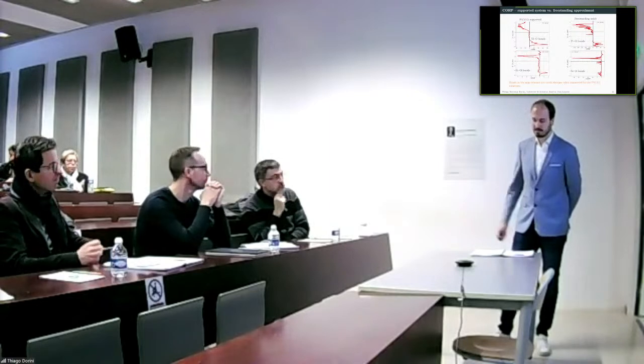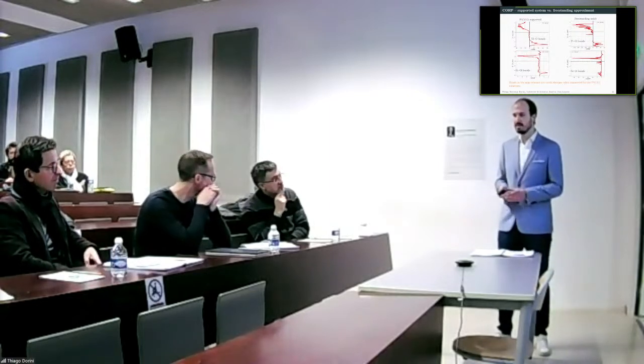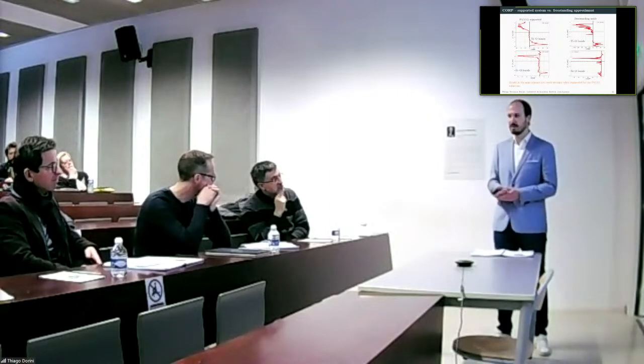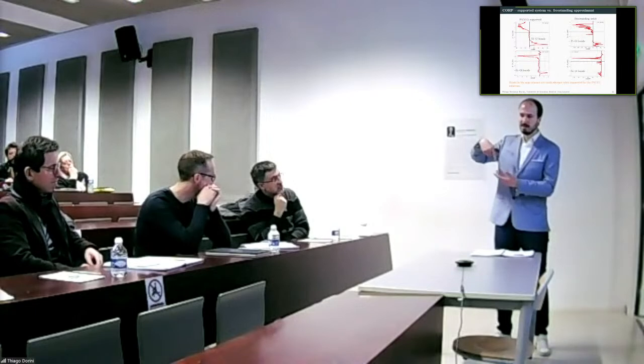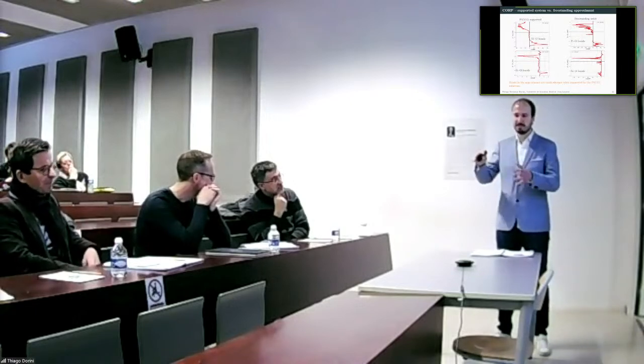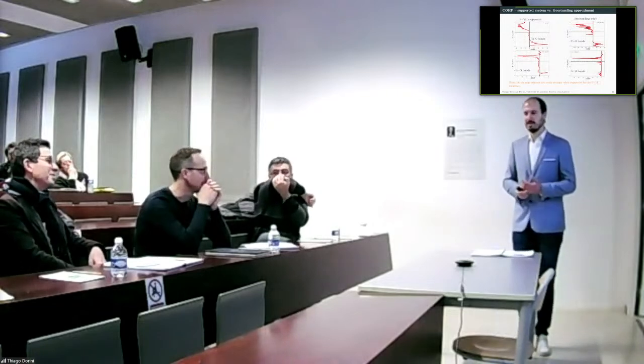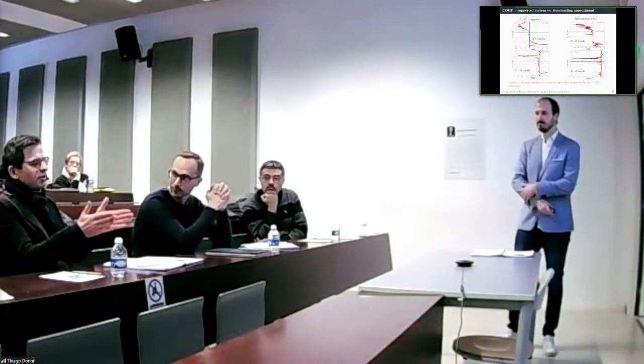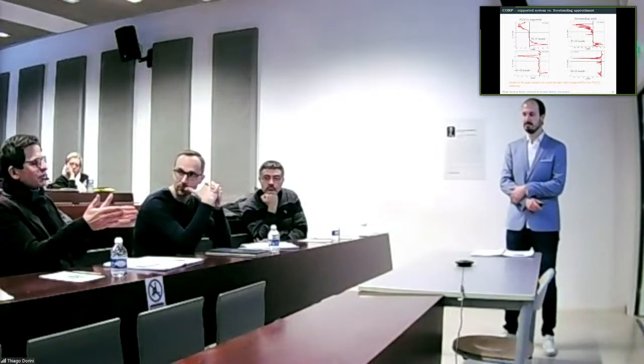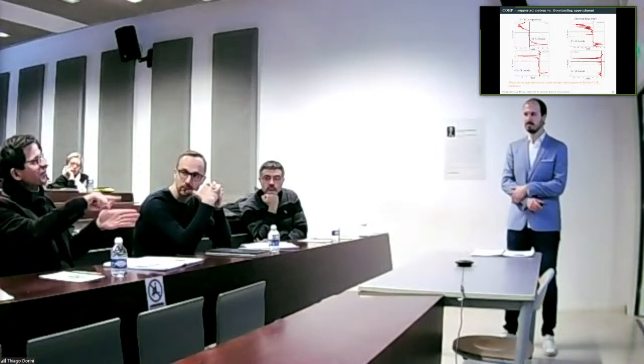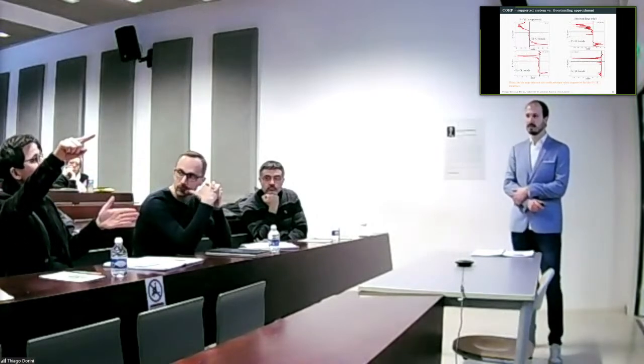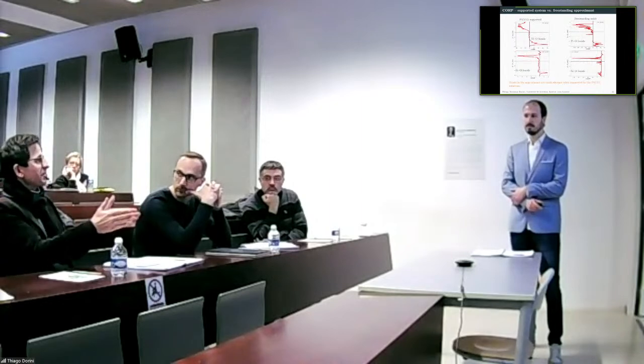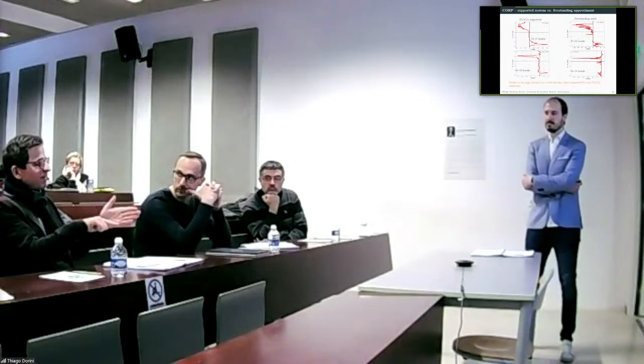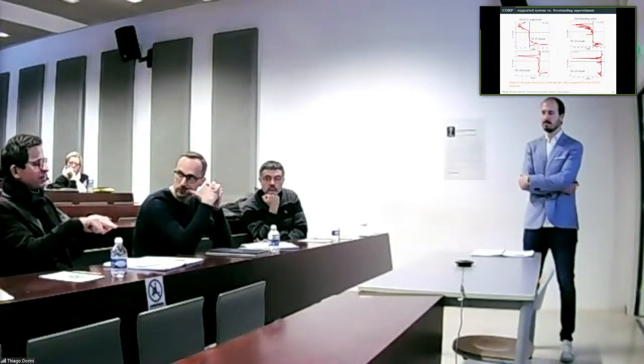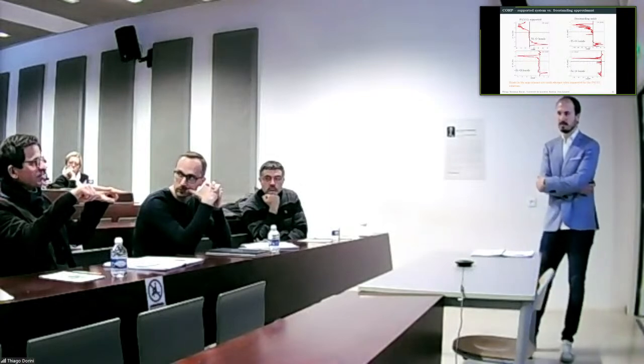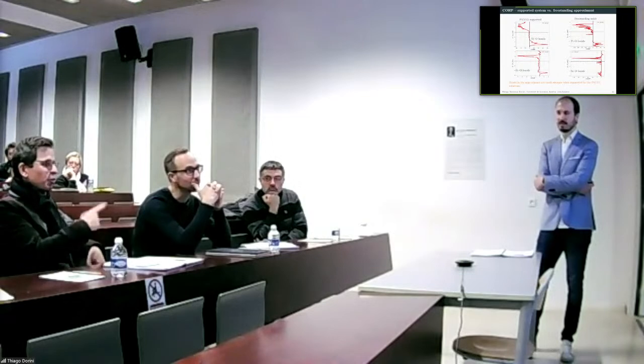Okay. Yeah, one thing that we have done, but it's kind of a trick, is that I know you are aware of the dipole correction, where we apply a field in the different directions to have a negative charge at the end of the unit cell. Well, this is a tricky point, in fact, because your film is symmetric. So many people say, okay, the argument I have just given, that you have an electrostatic potential that diverges with thickness, cannot be applied because it's symmetric, so it is not polar. And this is not true. In fact, you have a divergence between the center of the slab and the surfaces that goes symmetrically to the two surfaces. So the dipole corrections will not help.